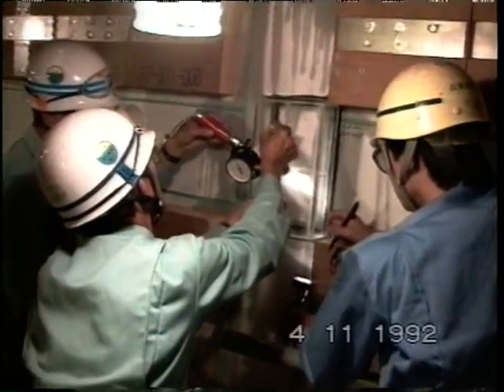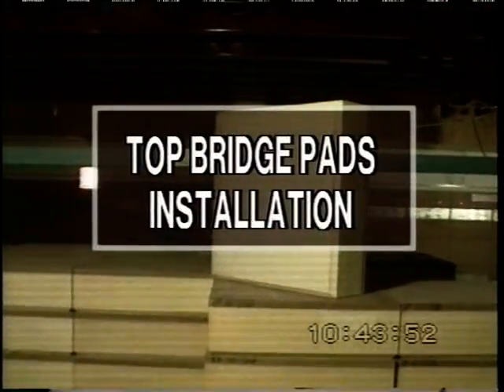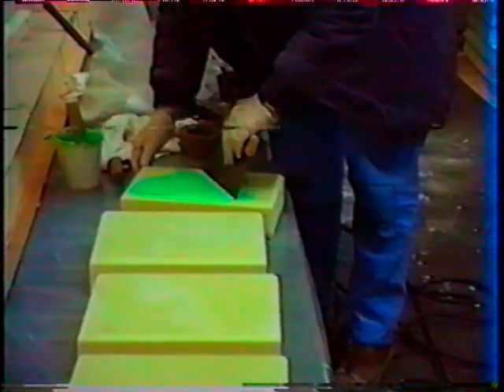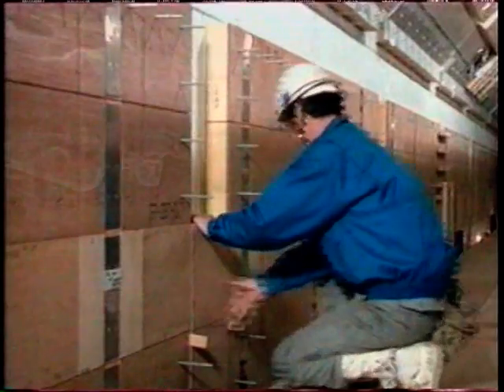At the same time, a rigorous inspection of the bonded crossover point is performed with a vacuum box and a soap solution for a bubble test. Square 340mm by 76mm thick bridge pads, prefabricated in the shop in the same insulating material and covered with plywood, are bonded and fixed to the secondary barrier scab to complete the primary insulating layer between panels.